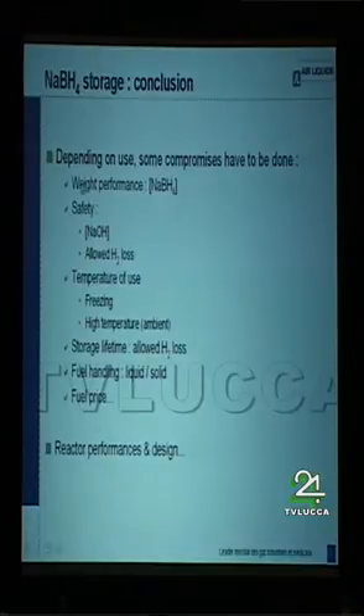The conclusion is that depending on use, we have to make some compromises for hydrogen storage in sodium borohydride. If we look at the weight performances, we need to increase the NaBH4 concentration. If we look at safety, we need to be careful of the amount of sodium hydroxide used in the solution, because it's a highly corrosive product. Moreover, always for safety, we need to define an allowed loss of hydrogen in the storage. Most of all, temperature is an important parameter to define, and we need to be careful of freezing.